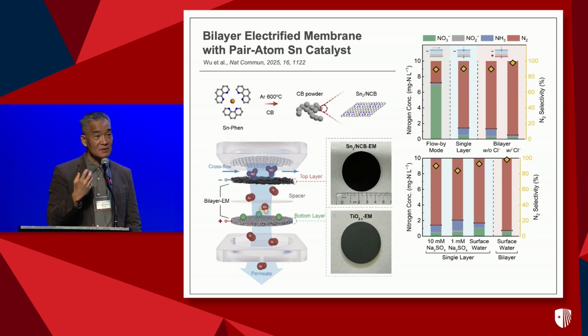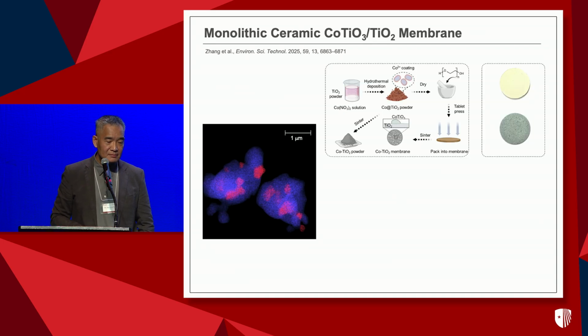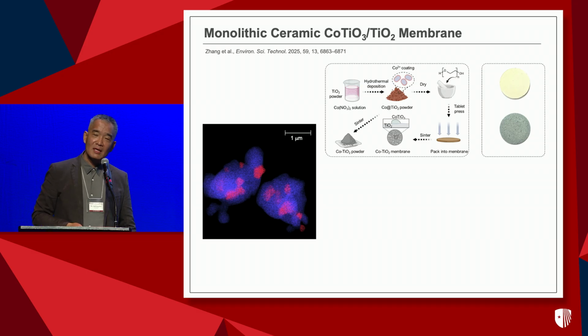That is one of the biggest problems when we are thinking about catalytic water treatment in any realistic system. So we keep thinking about how we can make our catalyst more stable. In the case of cobalt, we have done many different designs. If we load cobalt in any form onto a certain substrate, it leaches out over time, no matter what we do.